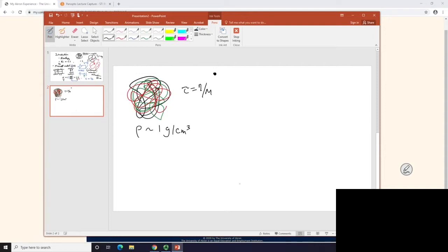To understand processing, to understand rheology, is to understand its molecular origin. So what is a molecular perspective or molecular expression, better yet, simply for tau? And this is not a trivial question. It was not answered until the 1970s. Even though last time I told you that when the chains are sufficiently long, your tau is actually proportional to molecular weight to the 3.4 power. So is viscosity.